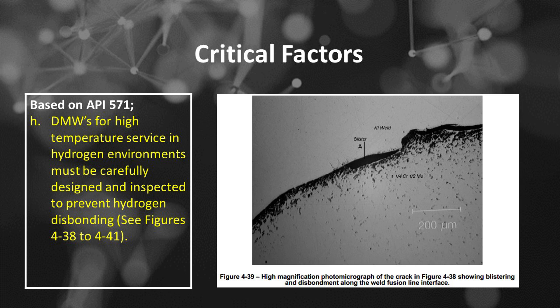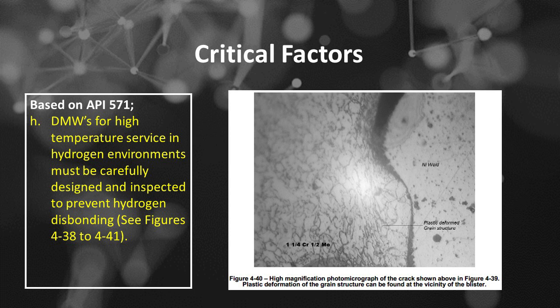See Figure 4:39, high magnification photomicrograph of the crack in Figure 4:38 showing blistering and disbondment along the weld fusion line interface. See Figure 4:40, high magnification photomicrograph of the crack shown above in Figure 4:39. Plastic deformation of the grain structure can be found in the vicinity of the blister.